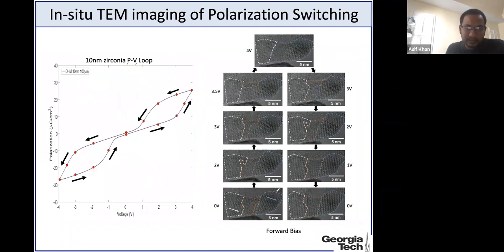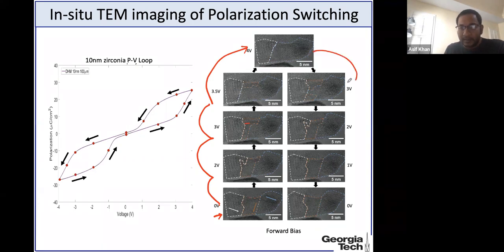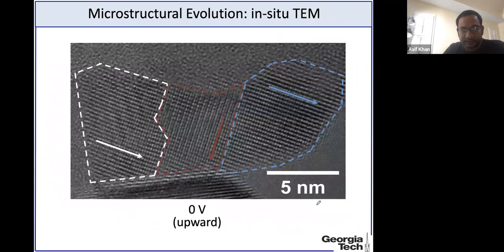So this is a quick overview of what is happening over here. Initially we have 3 domains within the grain. As we increase the voltage, we see that the middle grain is changing. And finally, when we go to 4 volts, the middle grain completely goes away. But when we come back, the middle grain starts to reappear, and finally we get back the original 3 domain structure.